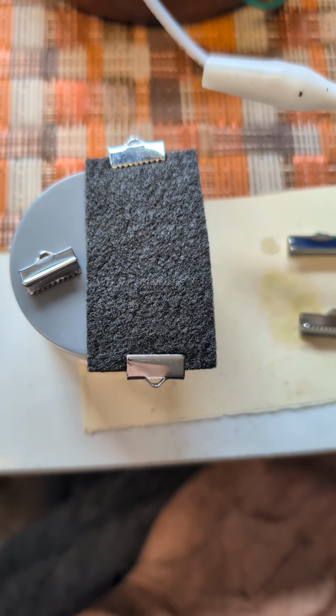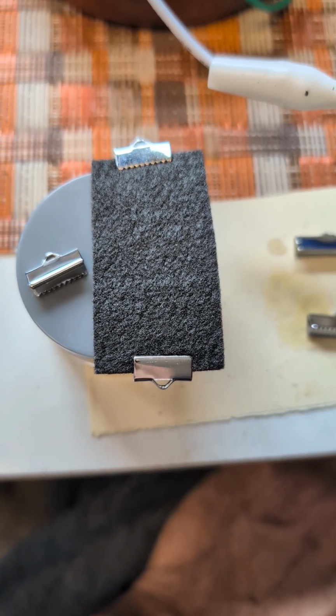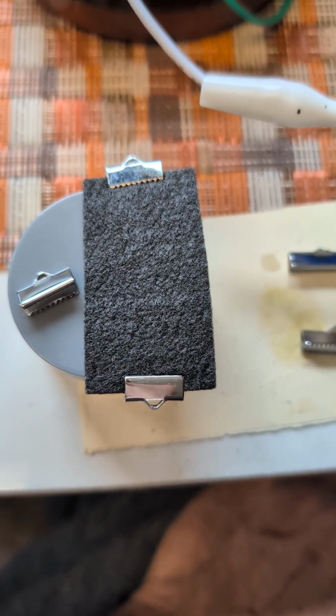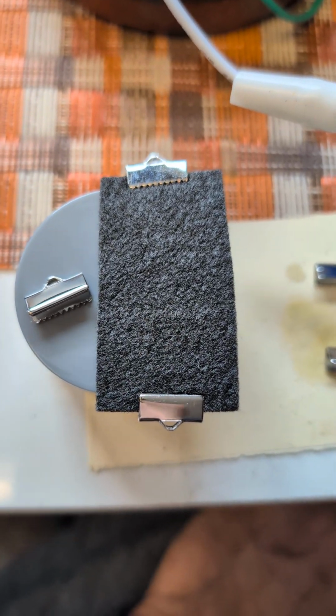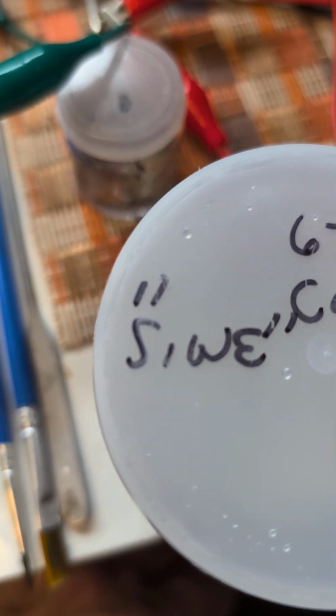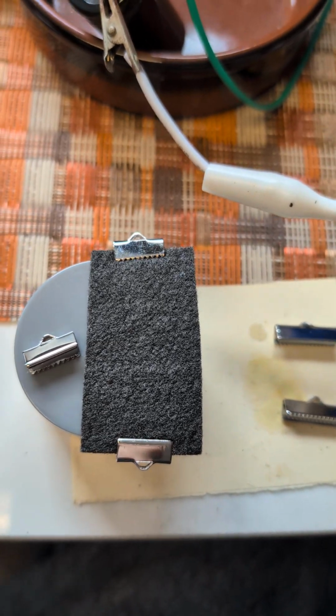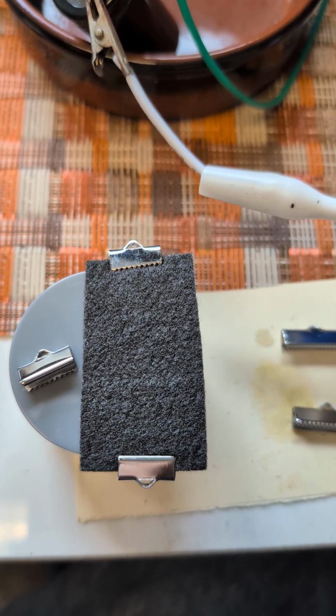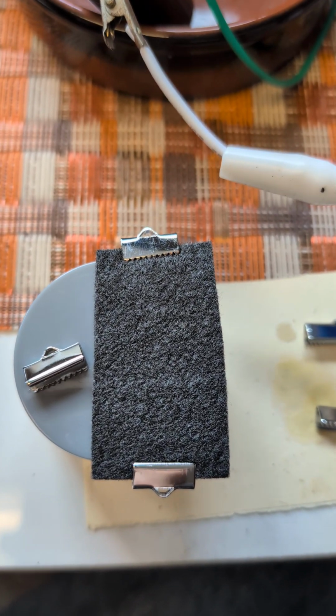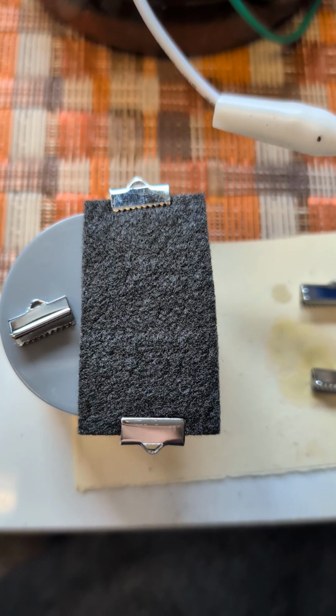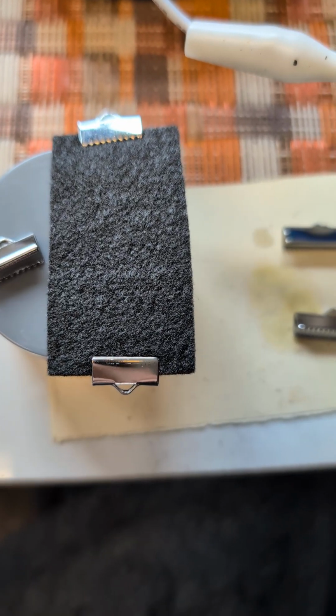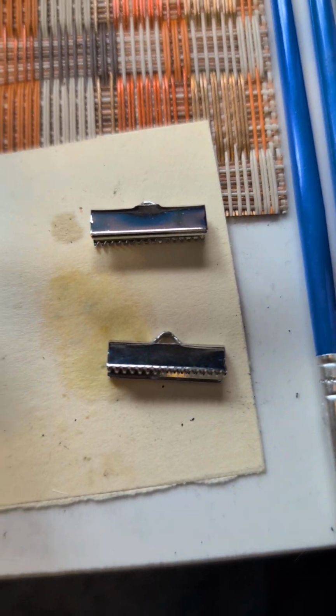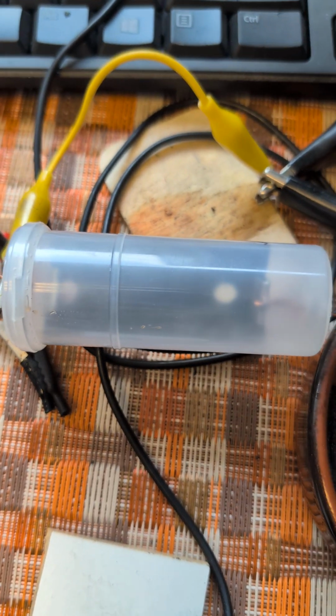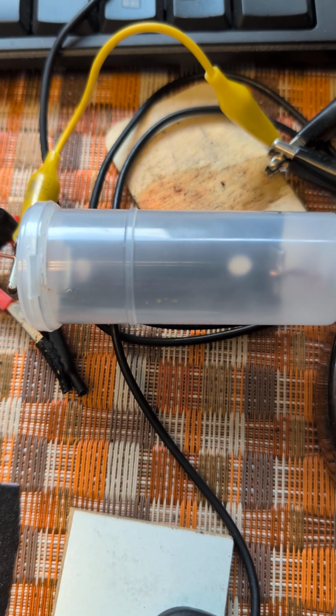Now, normally with an aqueous-based electrolyte, what are we looking at? 1.2 volts? Maybe 1.3 volts. With some of these salt in water electrolytes, you're getting incredible potentials. 2.5, even into the 3.0 range of potential. So that's what we're working on, and even the leads have to be cleaned. But we're up and running, and of course, the container just preserves the solution.